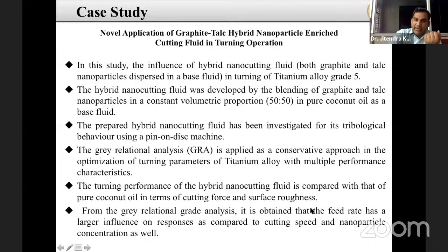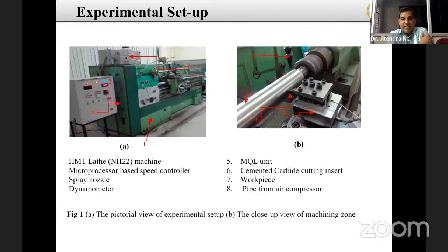From the grey relational analysis (GRA), we observed that feed rate has a larger influence on the responses compared to cutting speed and nanoparticle concentration. This is the machine I used. This is the dynamometer, and this is the MQL setup, which is 5 centimeters away from the tool-chip interface. This is the titanium rod, and we performed the experiment on this setup.